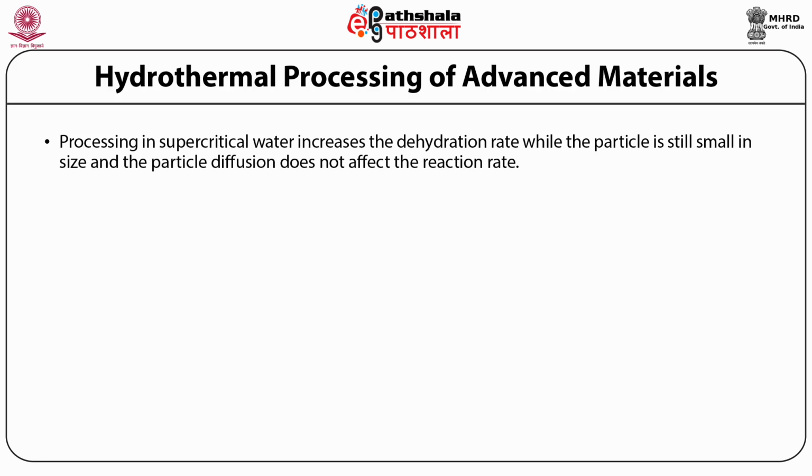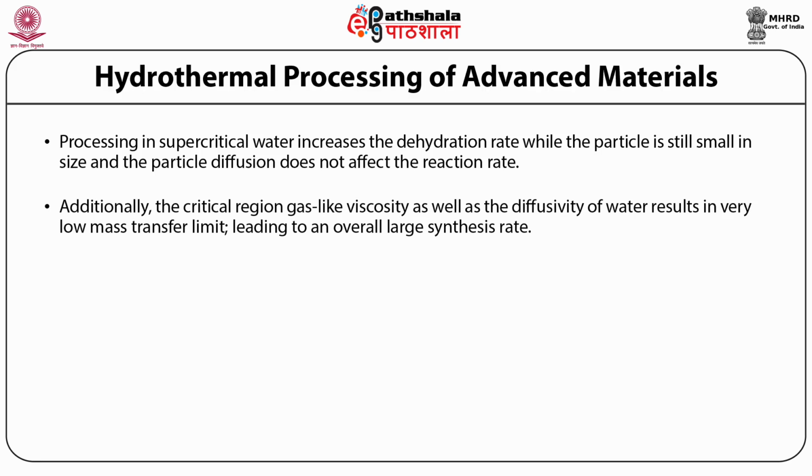Processing in supercritical water increases the dehydration rate while the particle is still small in size, and the particle diffusion does not affect the reaction rate. Additionally, near the critical region, the gas-like viscosity as well as the diffusivity of water results in very low mass transfer limitation, leading to an overall large synthesis rate.